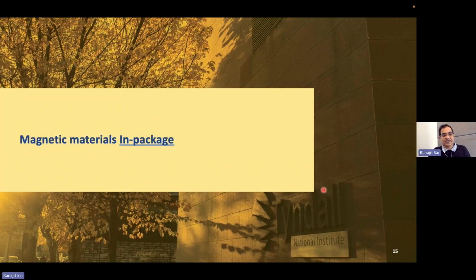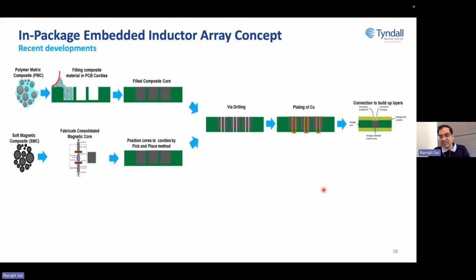I will take you first through the in-package activity of what we are doing. So here, this is how it is in terms of the concept. You start with a polymer composite matrix or a surface passivated soft magnetic material, and then make a magnetic block, or here in this case a slurry, and then fill this, and then you will get a filled composite core, or position the core in the cavities by pick and place method.